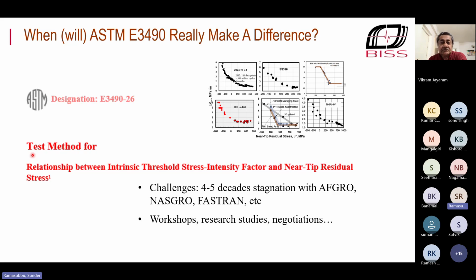Your question, Jaya, brings my memory back to a PhD work which was done by Quinton Bowles in Delft University in the mid-70s. And what Quinton did was to grow a crack in high vacuum and then continue the test in air. And then go back to vacuum. And what he found, his deduction was not a direct deduction, but a very reliable one. Because, in air, striations will form. But in vacuum, striations don't form for various reasons.